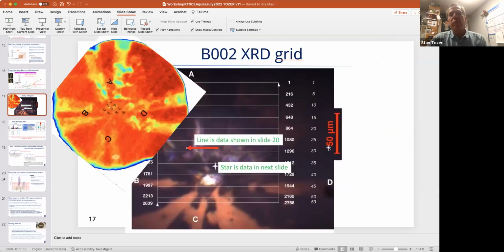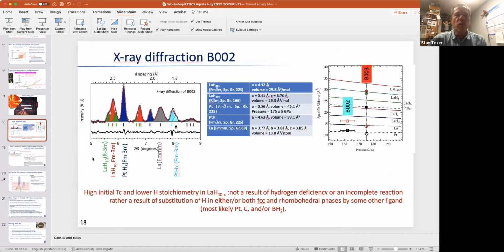So Audrey, at that point, a couple months later, went to DESY and obtained the X-ray data. I'm going to show data looking across this line. Later, we're going to look at the star first, where we see FCC and rhombohedral LaH_x. We also see a platinum hydride, PtH, and residual lanthanum and platinum. So we have a mess in there, but the good thing is we also have markers. These markers for lanthanum and platinum fall right on 175 GPa if you do the volume reductions.